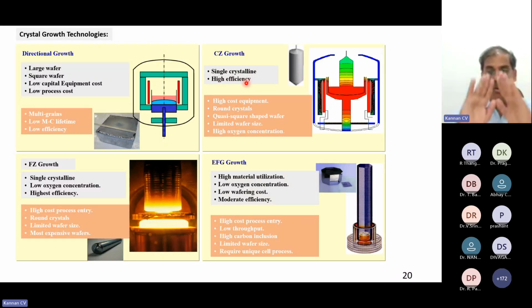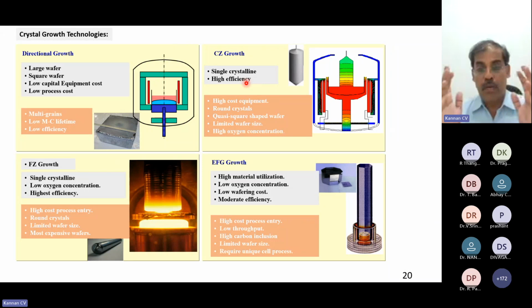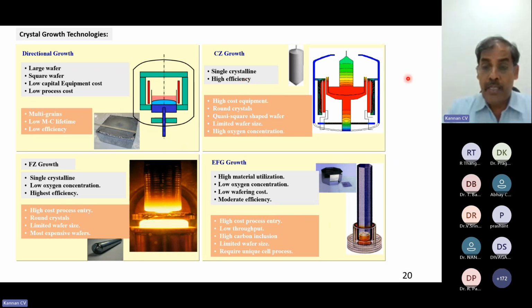Not only that, when you grow a single round crystal, and if you want to make a square wafer, you have to cut it down, so a lot of yield loss will be there. So overall manufacturing cost will be relatively higher, and also cost of the equipment is very high, and you can grow only round crystal, and you can make only quasi square. You cannot make fully square wafer, or different sizes also. And also in this case, the oxygen concentration will be very high, whereas in the multi-crystal DSS growth, oxygen concentration is very low. So there are some advantages in terms of efficiency, but there are some disadvantages.